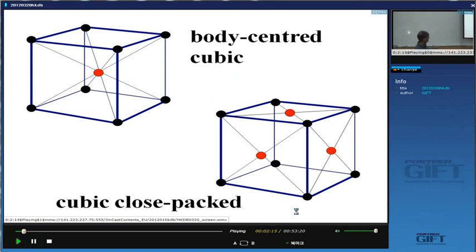And body-centered cubic. And we need to know how to deform this into this so that we can achieve the transformation without any diffusion. Okay? So is there some kind of deformation which will change this structure into this? It looks unlikely. They look quite different, but actually this problem was solved back in 1924 by Bain.